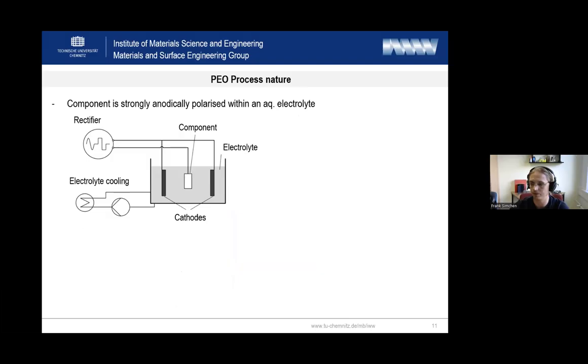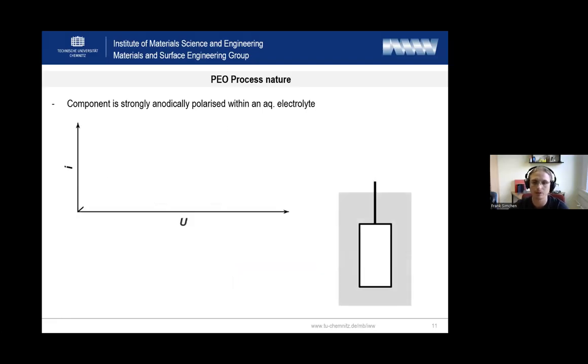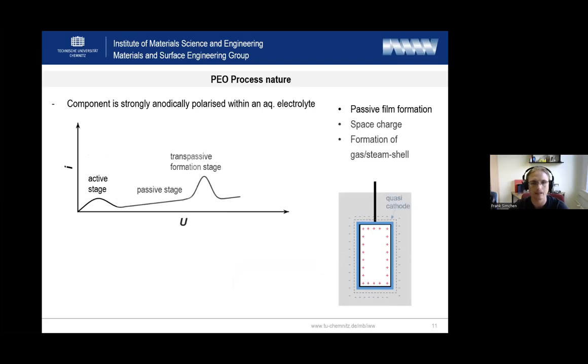Our working piece is placed into a passivating electrolyte and receives the alternating polarization. And during the anodic half cycle, various electrochemical and plasma chemical sub-processes take place, which I will mention here based on a schematic representation of the sample and an exemplary current density potential curve. So first of all, we have our naked working piece. Then we apply the first step of polarization, and this leads to the formation of an electrical isolating reaction layer, the so-called passive film.